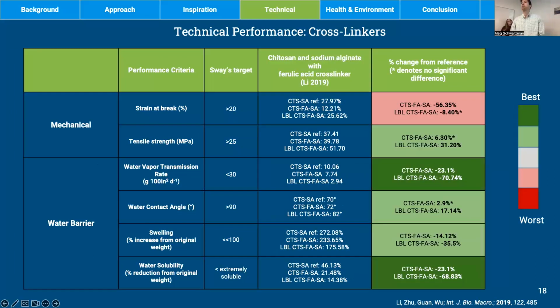All right, so moving on to our final strategy addressed here, the use of cross-linkers to improve moisture barrier properties. So this chart or table is based off a study in which chitosan and sodium alginate were cross-linked via ferulic acid, and these mechanical and water barrier metrics were assessed. Some things to note were there's a 1-to-1 ratio of chitosan and sodium alginate utilized.